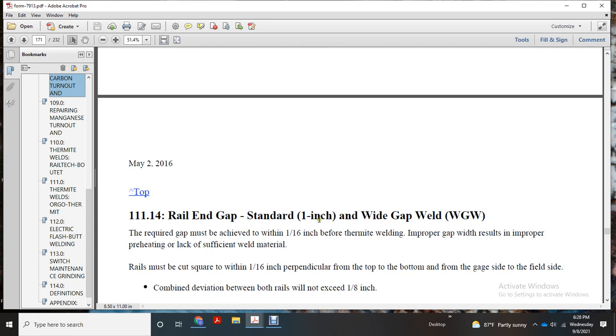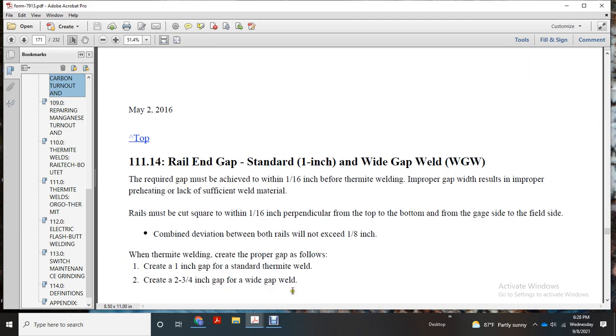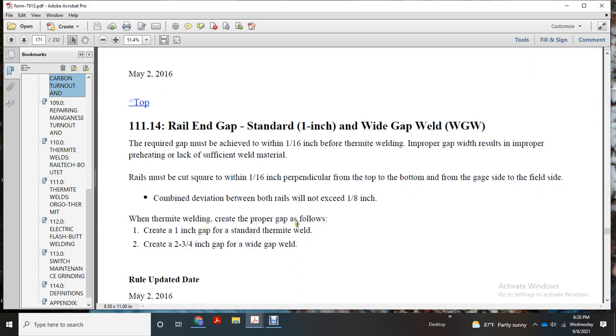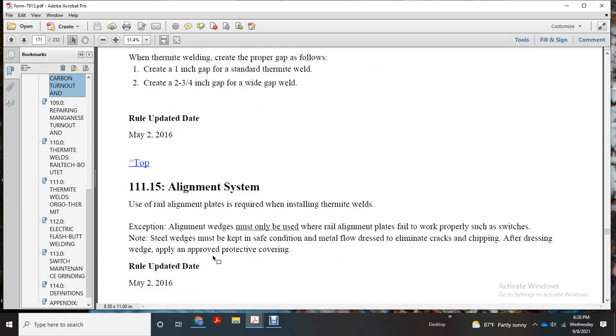Rail end gap: standard, 1 inch wide gap weld. The required gap is achieved within 1/16 inch before the thermite weld. Improper gap width results in improper preheating and lack of sufficient weld material. Rail must be cut square within 1/16 of an inch, perpendicular to the top and bottom, from the gauge side to the field side, with the combined deviation on both rails not exceeding 1/8 of an inch. When the thermite weld is created with the proper gap, it's followed with a create a 1 inch gap for the standard thermite weld, and a graded 2 3/4 inch gap for the wide gap weld alignment system.